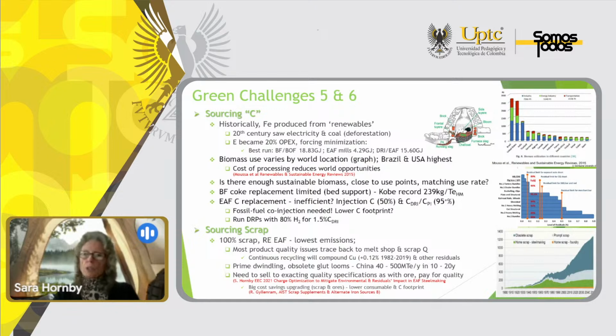Now, the fossil fuel co-injection is often needed with the biomass, which of course is not necessarily going to lower the footprint for the carbon. So I'm suggesting that we don't negate all of the carbon from the DRI, that we potentially run with 80% hydrogen, which would give us 1 to 1.5% of carbon still in the DRI. And I'll explain why that's important.